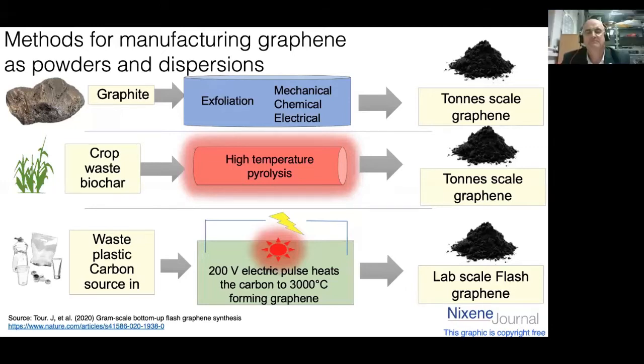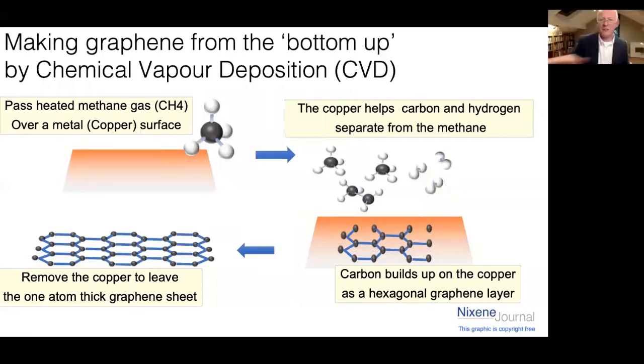Yeah, good point, Mike. Chemical vapor deposition graphene. Do you remember I showed you that metal foil with graphene on? This is how it's made. You start off with methane, CH4, the black bit in the middle is carbon, the white spheres are hydrogen. Basically, you're ripping off the hydrogens and the carbon atoms line up onto the copper foil or the metal foil, and they connect together in the lowest energy shape they can, which turns out to be this hexagonal chicken wire lattice. And then once the surface is covered, the reaction stops. And then you can peel off the graphene or dissolve the copper away to leave the graphene sheet.